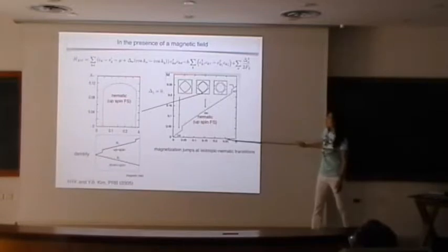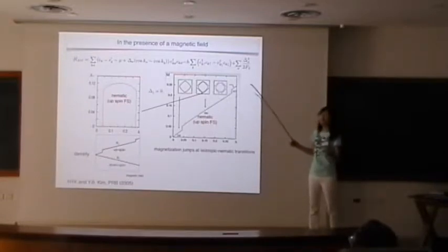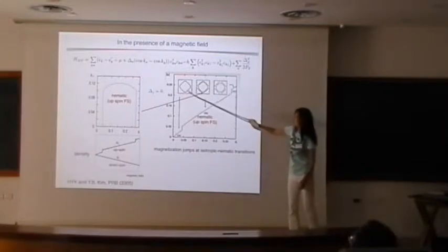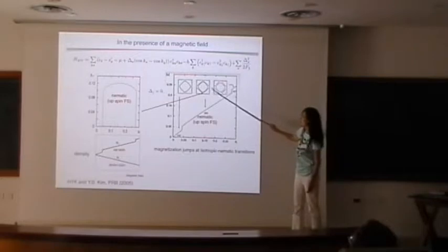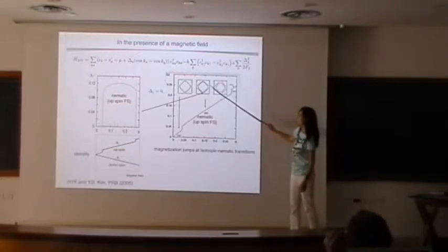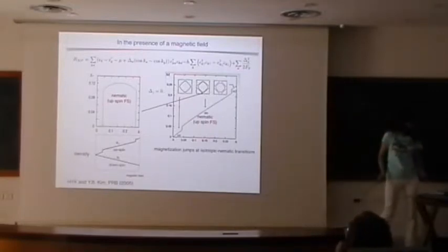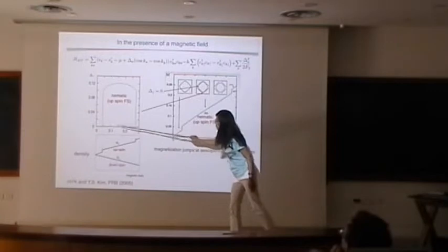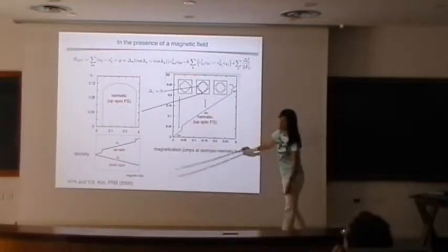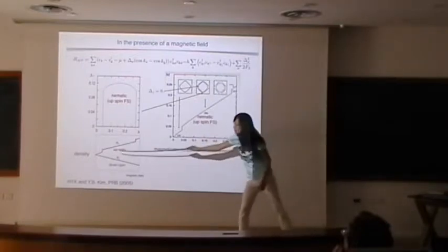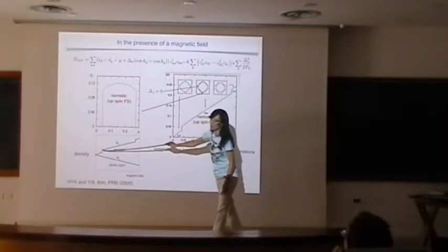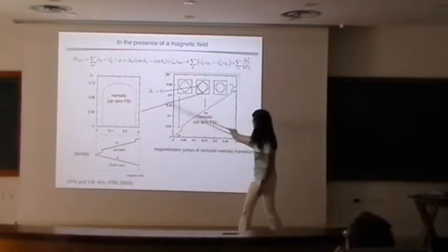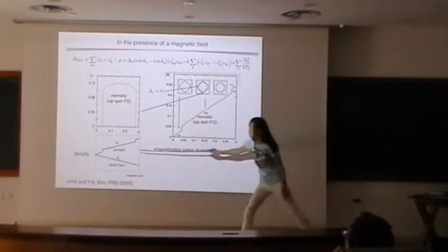And as I further increase, the up Fermi surface will get bigger and bigger, and now I'm going far from the Van Hove singularity, so it won't suffer from this distortion, and goes back to isotropic. So from electron-like to hole-like, you go through the Van Hove singularity, but only the up Fermi surface has to be distorted, while the down Fermi surface doesn't have to. And that gives a delta for the up spin that is finite within the window here, while the down spin is basically at zero. Since it's a first-order transition by definition, the density has to jump where delta is finite, but only in the up spin, and then it has to jump again where it goes back from nematic to isotropic. On the other hand, the down spin, which is not suffering through this interaction effect, will just continuously decrease.